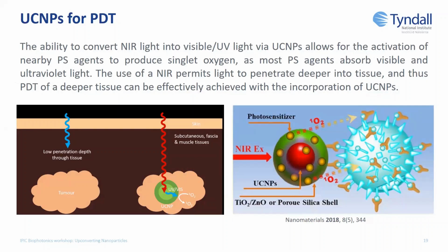So when we are treating deeper seated tumors, it's actually that the light cannot reach them. So we could use upconverting nanoparticles because they are excited in near infrared, and they can emit also the visible light to reach deeper seated tumors while exciting the photosensitizer at the same time.